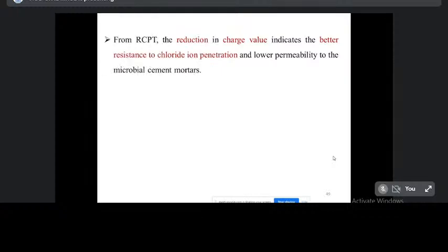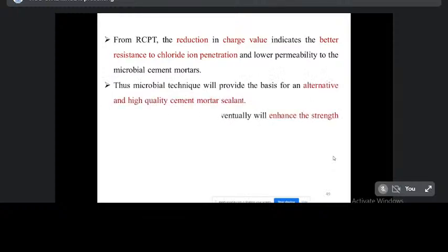From the RCP test, the reduction in charge value indicates better resistance to chloride ion penetration and lower permeability of the microbial cement mortars. This microbial technique will provide the basis for an alternative high quality cement mortar specimen sealant. It is environmentally safe and eventually will enhance the strength and durability properties of the building material.